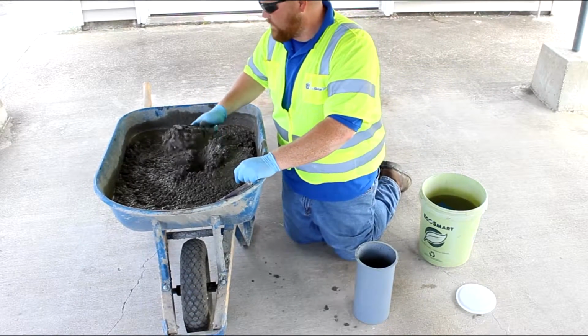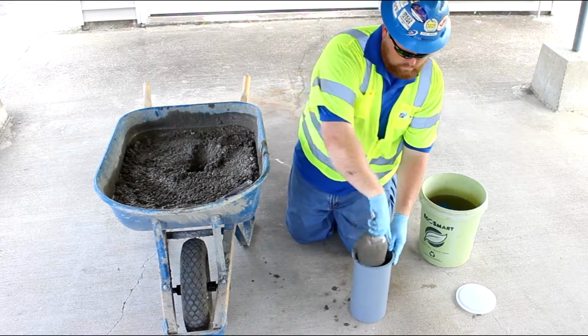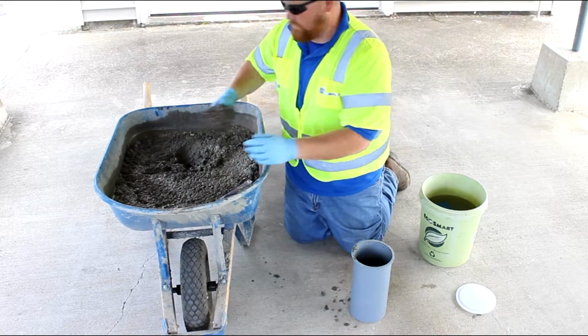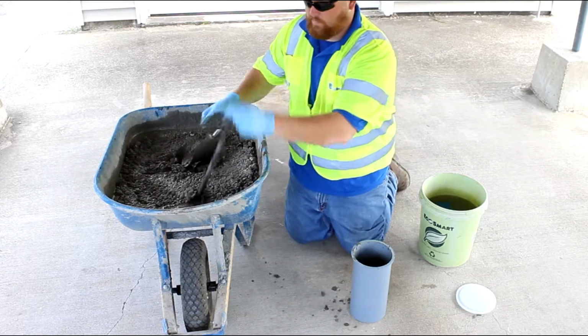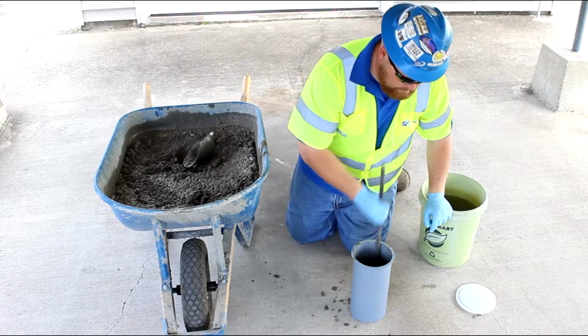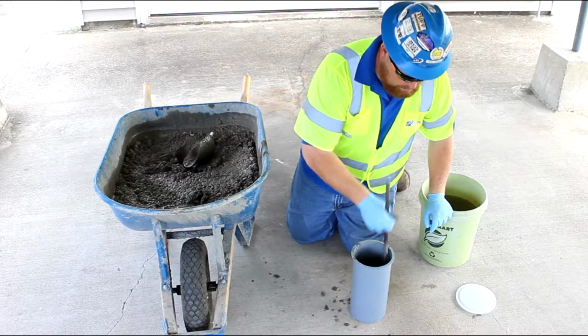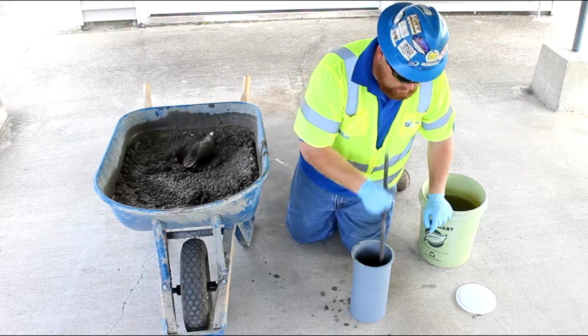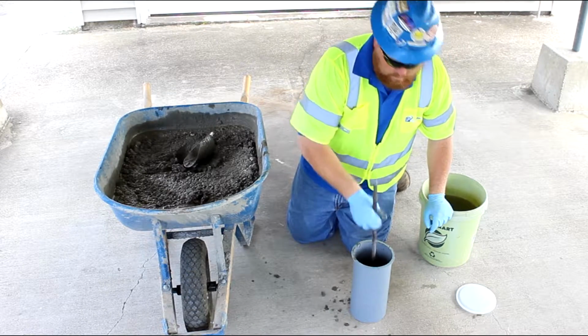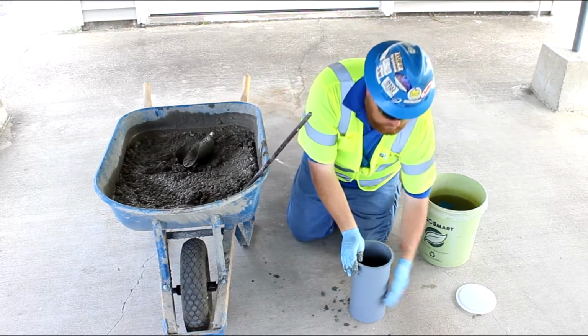Mark the specimen to positively identify the concrete it represents. Place the mold on a level surface. Use a scoop to place concrete in the mold. Use care to distribute the material evenly around the perimeter of the mold. Fill the mold in 3 equal lifts. Rod each lift 25 times uniformly over the cross-section with a rounded end of the rod.